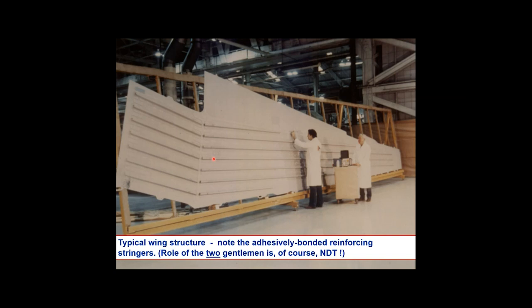This shows a typical wing structure from an aircraft. It's actually a British Aerospace 146. And here we see the U-shaped stringers which are bonded on. You obviously can't see the adhesive, but these are the stringers that are bonded on. These two gentlemen, as you might guess, are doing non-destructive testing. They're using an ultrasonic probe here to actually see if the adhesive is in place, is sufficiently cured, and it's of the right thickness.